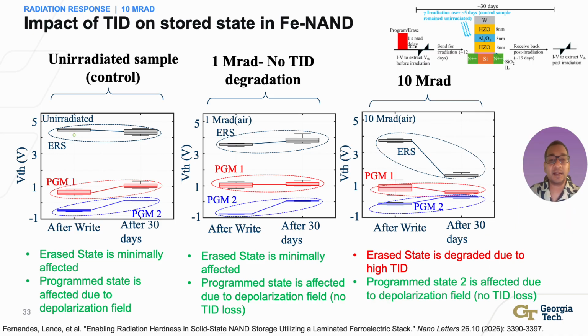At 10 megarad, a distinct dose effect emerges. The erased state shifts more than the control and 1 megarad samples, while the program states remain dominated by the same depolarization related relaxation. The behavior is asymmetric, which points to radiation created traps and interface electrostatics, rather than a simple destruction of the ferroelectric polarization.